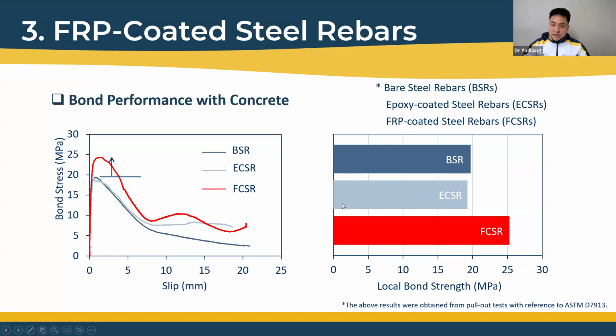I think partially this is because of the enlargement of the diameter by the FRP coating layer. When calculating the local bond stress based on the pull-out test results, we just use the nominal diameter of the core steel rebar, not the overall diameter of the rebar.